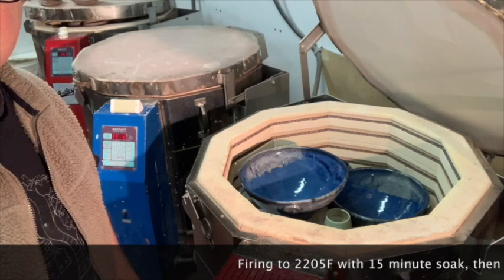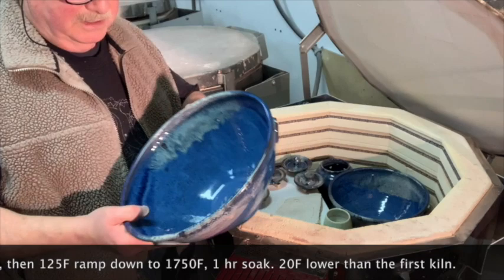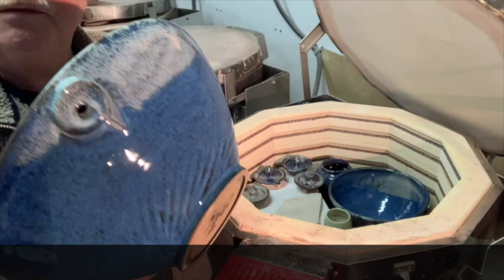Okay, all right, so let's show you. So my recycled clay, my wife uses a little bit of earthenware clay, and it gets mixed up into my slops, so when I fire the stoneware clays, you get a little bit of that earthenware clay in here, so it can bloat. And this one, no bloating, so just that, really, it's only like 25 degrees difference in firing temperature, but the bloating disappeared.